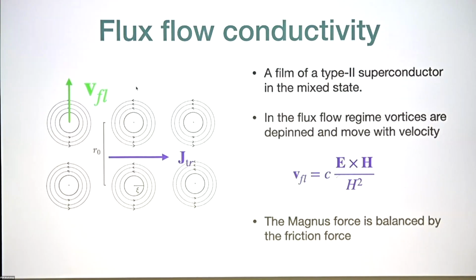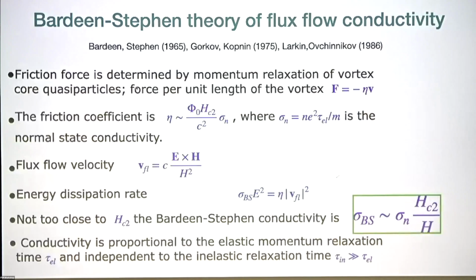In the flux flow regime, the pinning force becomes irrelevant, and the Magnus force is balanced by the friction force on the vortices. And the velocity of vortices is proportional to the electric field. That's essentially the Josephson relation. It's this drift velocity with which all the magnetic field lines drift. And in the traditional theory, the resistivity is all due to the friction of the vortex cores, which behave as chunks of normal metal. So let me start by reviewing how this theory goes, to offset what I'm going to discuss.